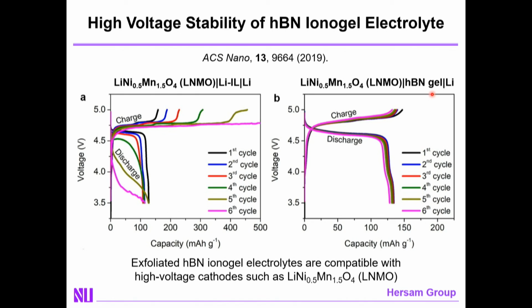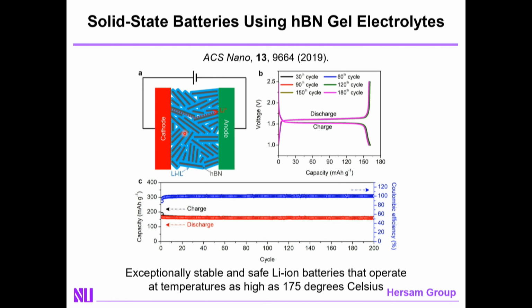Additionally, that strong interaction between the HBN and the ionic liquid implies that you get very high stability, particularly at high potentials. In this case, what I'm comparing is the ionic liquid alone compared to the HBN ionogel. And you can see at high charging voltages up to 5 volts, you get considerably higher stability than the liquid alone. You can then use this HBN ionogel to make a full solid state battery.